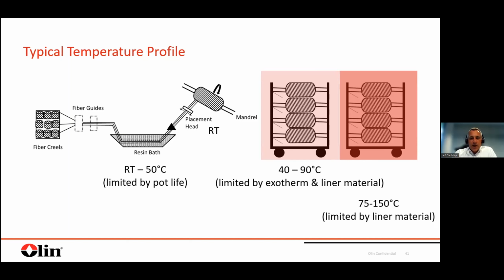Then the gelation is typically done, for some of our resins, it could be done at room temperature, but typically what we see is roughly between 40 and 90 degrees C. The limitation here is the exotherm in relation to the liner material. And for the post-cure, in the end, we see ranges from 75 up to 150 degrees C for high TG systems. Again, with the limitation upwards being the liner material at this point of time.